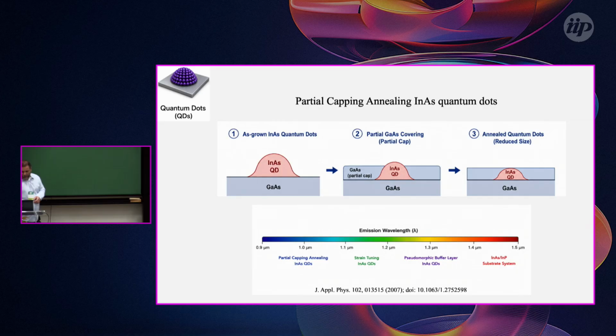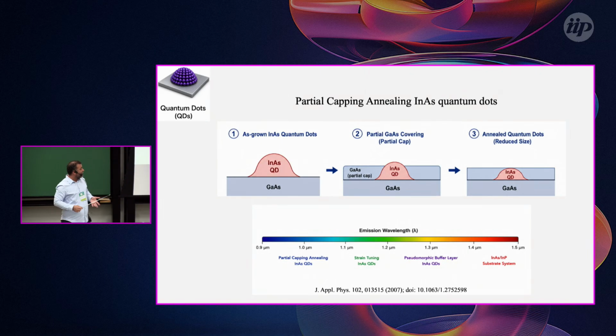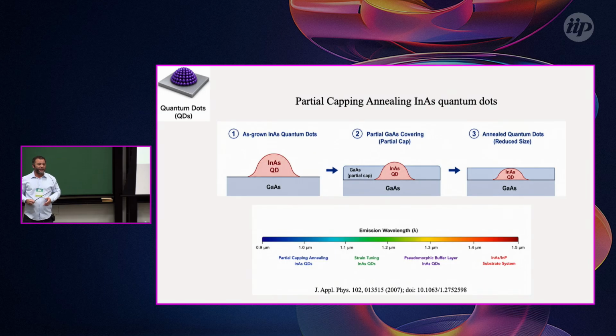But another one that Jorge showed is what I named partial capping annealing indium arsenide quantum dots. Basically, you grow an indium arsenide quantum dot. After this, you can deposit 2 nanometers of gallium arsenide, let's say at 500 degrees. If you ramp the temperature to, let's say, 600 degrees, this cap will evaporate. And with this, you can manage to shift the emission from 1.2, 1.1 microns to 900 nanometers. And this is what companies like Quandela and Sparrow Quantum that sell single photon sources are using now in the market.